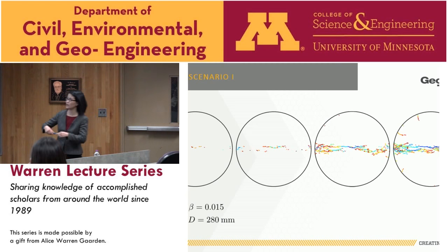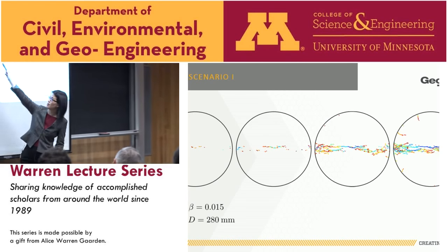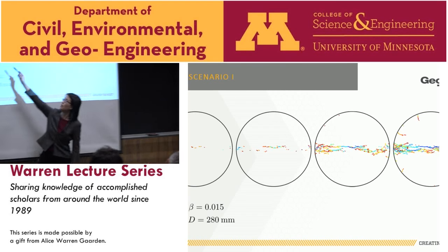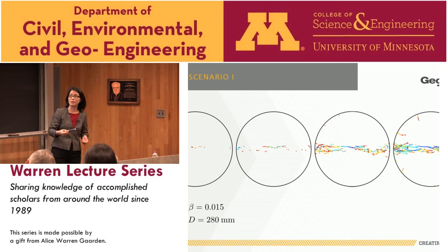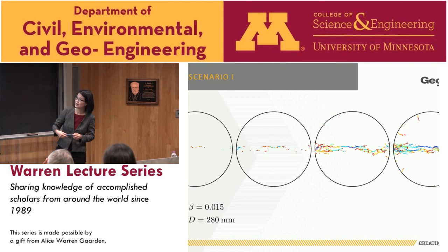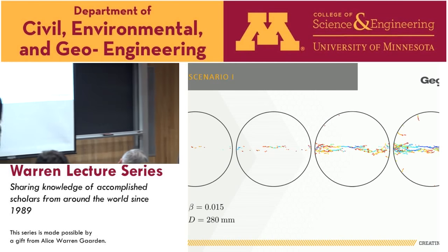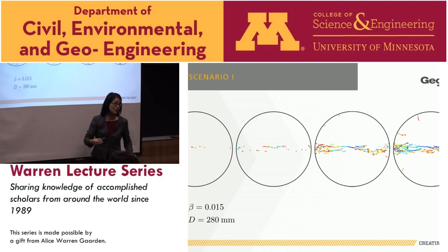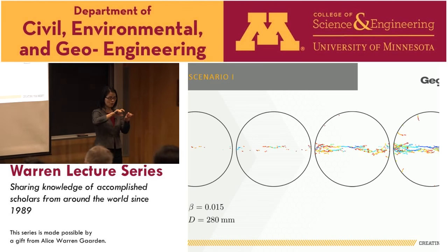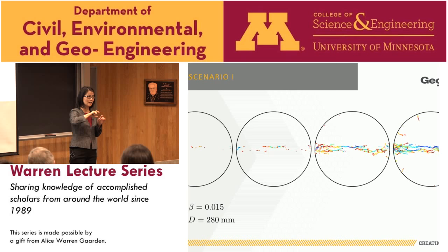In this case, you can think of it as a center crack developing immediately. Then top and bottom, if there are any softening bonds, you can characterize that as a process zone. But when I plot that, what I see is softening bonds starting from the edge all the way down. They are very clean two bands, extending from the crack tip to top and bottom.